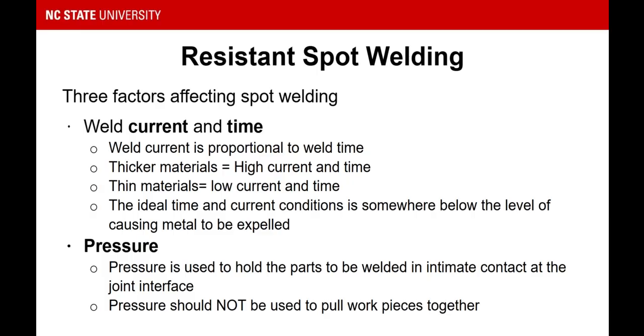The ideal time and current conditions are somewhere just below the level of causing metal to be expelled. So what you want to see is when you weld, you want to see the material turn red around the tips, and you want them to stay red. Okay? If you're not seeing red around the tips, you probably need more current and more time.